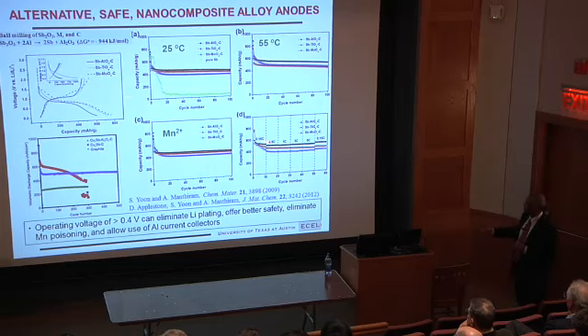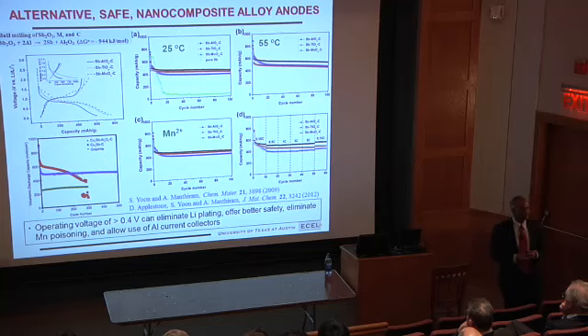Look at the rate capability. 1C means you get the whole capacity in 1 hour. 5C means you get the whole capacity in 1/5 of an hour. 0.5C means you get the whole capacity in 2 hours. So this is fast charge, and it doesn't change much. High rate capability systems. But I lose one thing.